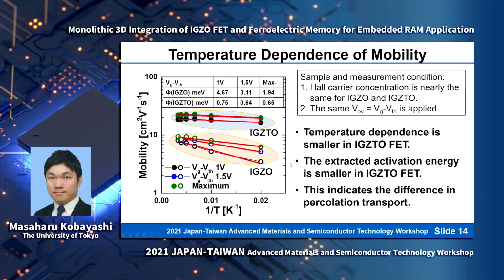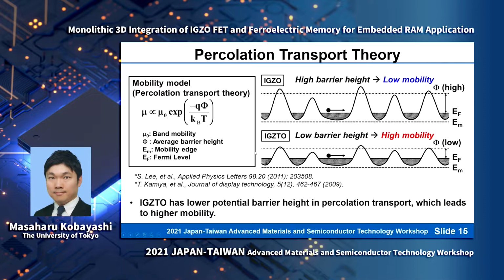Typically, based on the transport theory of amorphous IGZO transistors, the transport characteristics are described by the so-called percolation transport. So this indicates a difference in the percolation transport between the IGZTO transistor and the IGZO transistor. The mobility can be described by the percolation transport theory with an equation like this. The mobility is proportional to a constant times exponential of minus q phi over kBT. Phi is the average potential barrier height in the amorphous semiconductor.